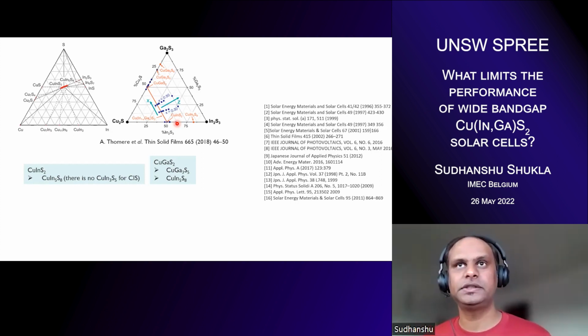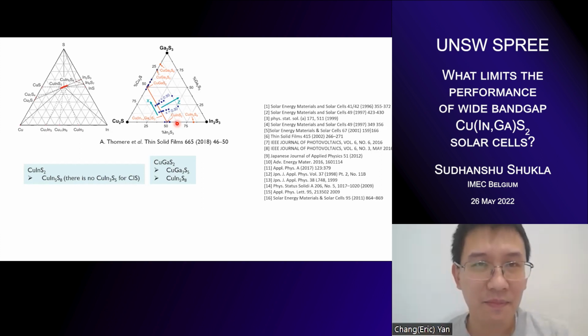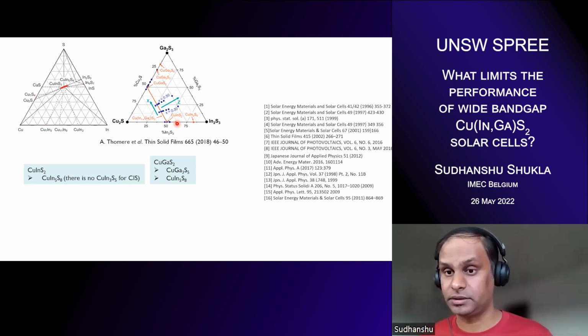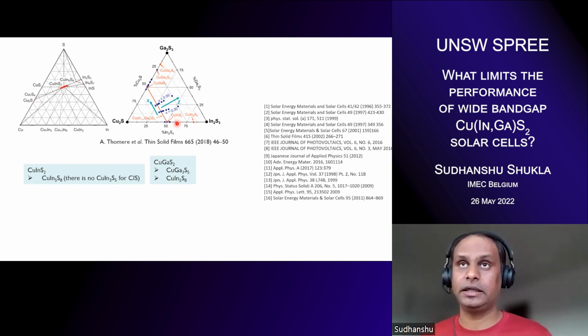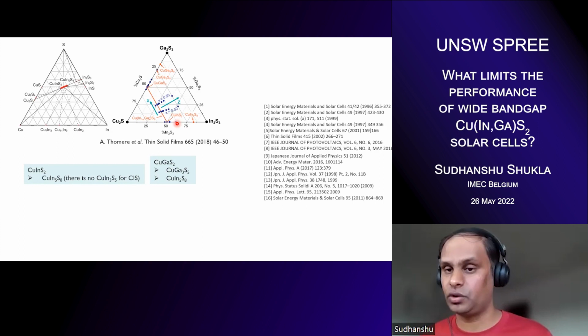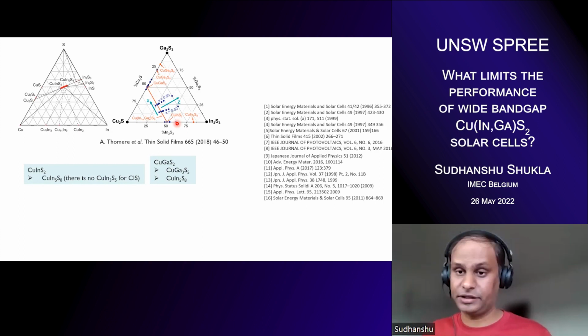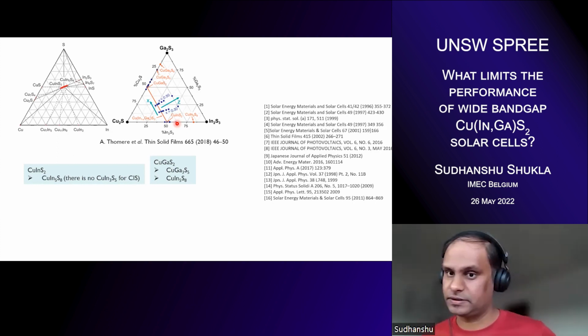The high efficiency cell that you saw, as I said, we are actually at the extreme of the composition where you start seeing very noticeable light soaking effects. So the JV was obtained after light soaking for 15 minutes, and that's why they used the similar protocols that they use for perovskites. So Fraunhofer ISE asked us whether we have this instability, this light soaking effect. So they applied the same protocols as they used for perovskites, and that's why they show this hysteresis.